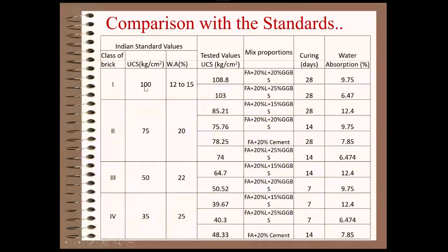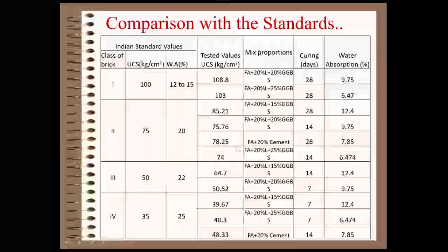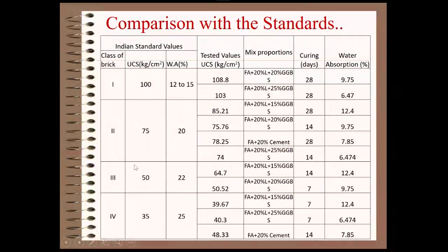For example, see, the IS code gave the different compressive strength values for the bricks, first class, second class, third class, fourth class bricks. For this, what are all the mixes satisfying the requirement? Based on our research, we understood these are all the mixes possible to get these strengths. That means brick making is possible if these mixes can be followed. And water absorption also satisfied. That is why these are all successful combinations we have written, because water absorption limits are also given for every category of the brick, and these mixes have satisfied those requirements also.